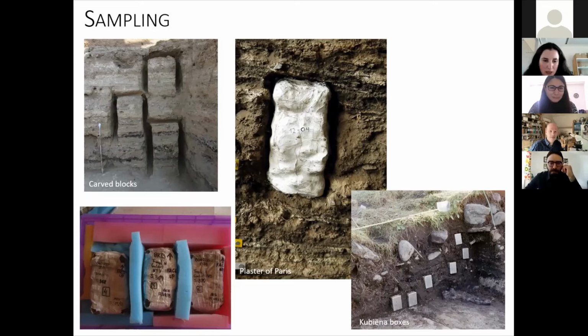The boxes have to be completely full. This is a very important aspect, because if movement is allowed inside of them, block samples might get scrunched and therefore disturbed. So in extreme cases where the samples were not properly wrapped and properly boxed, this has rendered samples unusable for micromorphological analysis, because they get too disturbed.